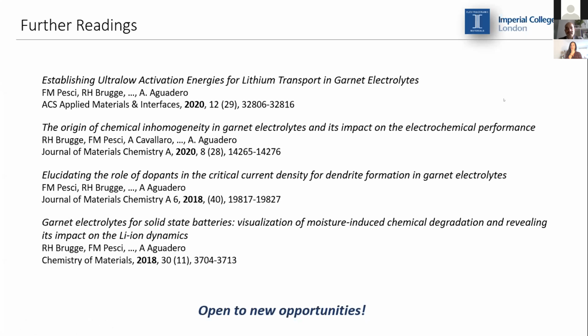We can definitely play with the grain size. In my experience, we haven't actually seen much difference in the interfacial resistance between larger or smaller grains. But the biggest difference has actually been the thermal treatment. So I'm not entirely sure if that would actually affect the interfacial resistance.